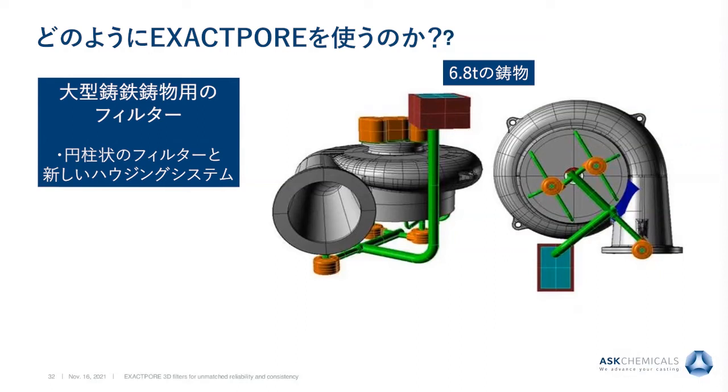When using an EXACTPORE housing system, the filters can be placed at the bottom of the contacts, allowing a pressure drop that backs up the runner system and reduces any reoxidation potential due to the acceleration of gravity. The runner system remains full, the alloy is filtered effectively with the filters, and laminar flow is created at the base of the contacts.